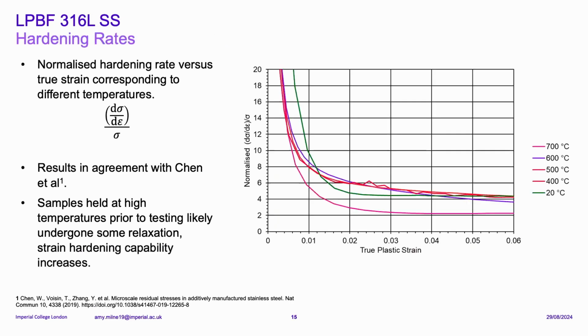I then looked at the hardening rates, and I plotted the normalized hardening rate against the true strain corresponding to different temperatures. Again, these results agree with literature. And as I mentioned before, the samples were held at high temperatures prior to testing. They likely underwent some relaxation, and so their strain hardening capability would have increased, although you can see it's quite similar for a lot of the mid-range temperatures there.